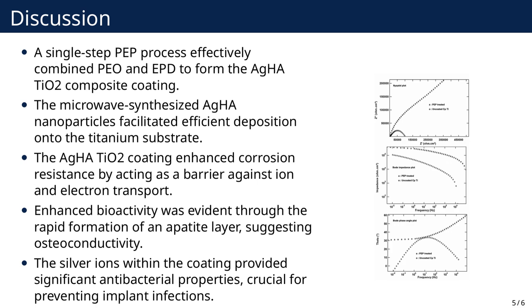The development of the AgHA-TiO2 composite coating on CPTi via PEP was achieved in a single step, combining PEO and EPD. The microwave synthesis produced nano-sized AgHA particles beneficial for subsequent deposition. The PEP process, carried out in a constant current mode, involves initial TiO2 formation through PEO, followed by the incorporation of AgHA particles via EPD as the potential increases with coating thickness.